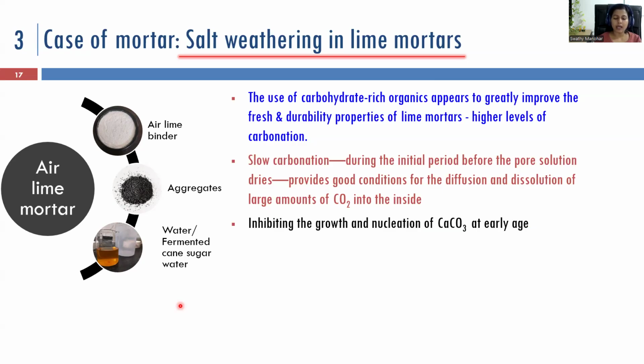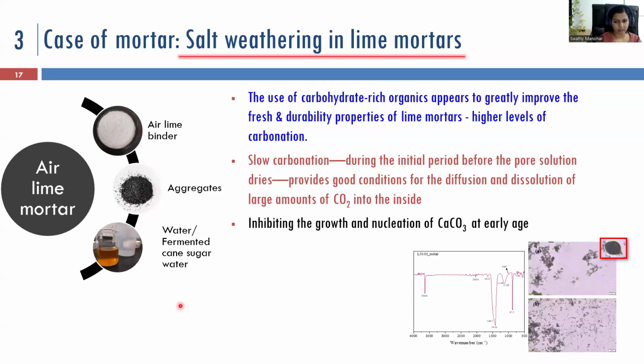They are told to have slow carbonation during the initial period before the pore solution dries, providing good conditions for the diffusion and dissolution of larger amounts of CO2 inside. So they coat around the calcium hydroxide particles, inhibiting the initial nucleation of CaCO3, so CO2 can easily get into the system and have better carbonation.